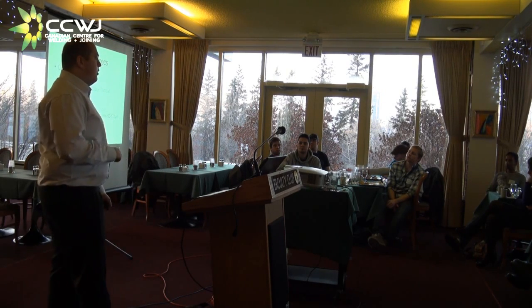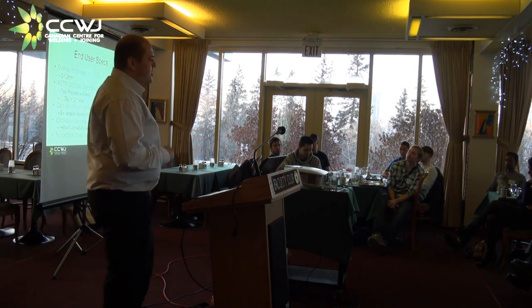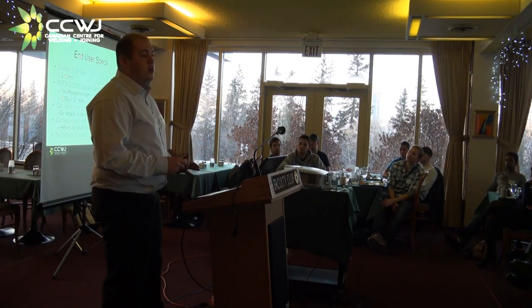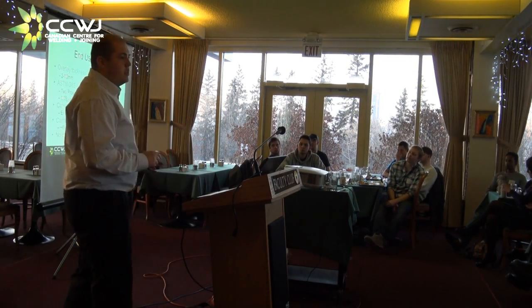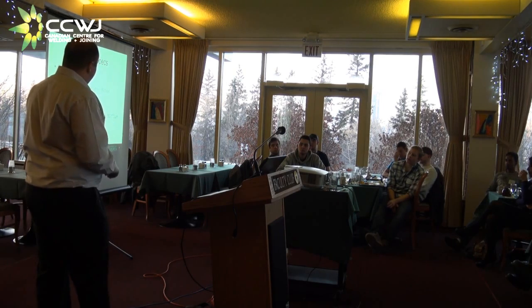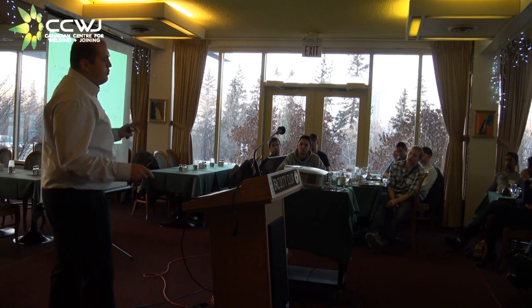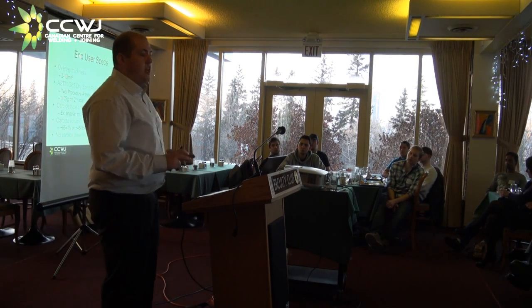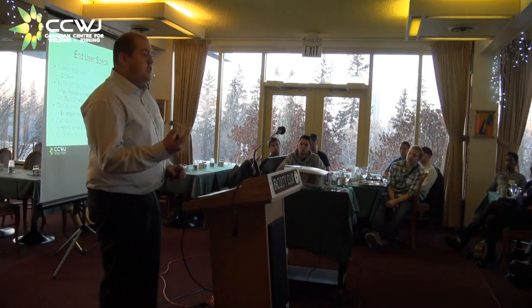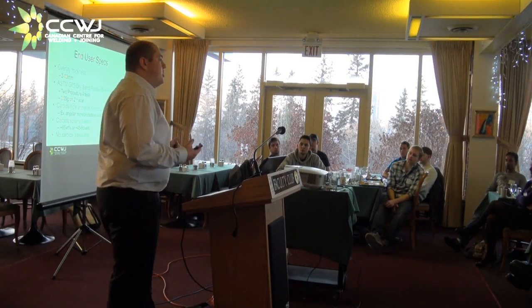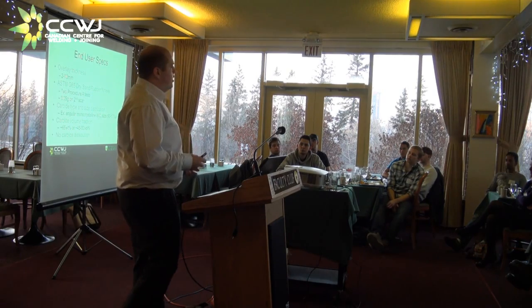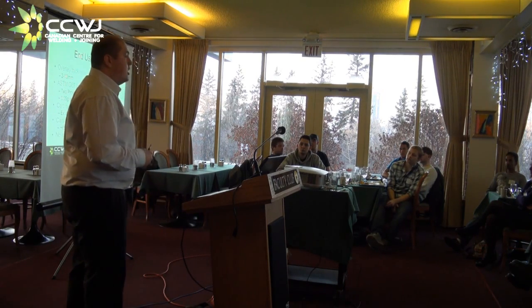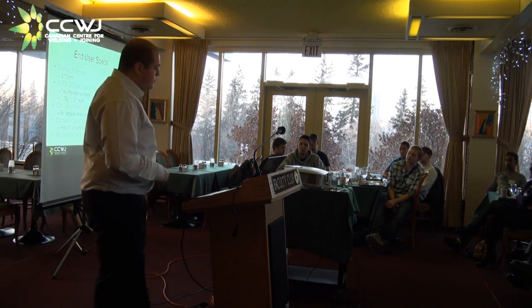One of the most important things with these overlays is actually having enough carbide in our deposit. Usually it's spec'd out as 65 weight percent of tungsten carbide, which roughly equates to about 50% by volume. So half is going to be tungsten carbide, half is going to be the nickel matrix. And this is really important, and we'll see why when we start looking at these tubular consumables.